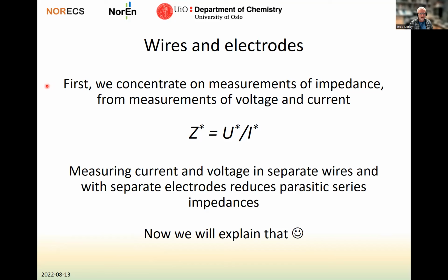When we talk about wires and electrodes to do the measurements, first we concentrate on measurements of impedance from measurements of voltage and current. The complex impedance is the ratio between the complex voltage and the complex current. If you do DC measurements, these are simple numbers, and if you do AC measurements, these are complex numbers. Measuring current and voltage in separate wires and with separate electrodes reduces parasitic series impedances. Now we will explain that.